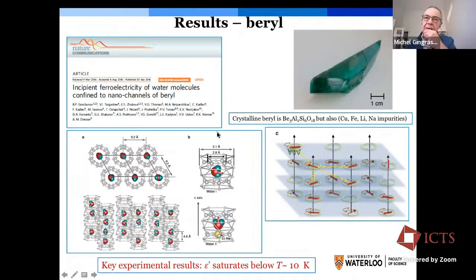Sure. Thank you. So beryl is interesting. These are gemstones like emerald and so on. And what one finds in these systems is that they don't form a face-centered cubic lattice, but in fact they are hexagonal structures where there are cages that can host the water molecules, which form a hexagonal lattice. So one has an AAA type stacking of the dipoles, which is illustrated here, and the occupation of those cages is of the order of 30 to 50%.